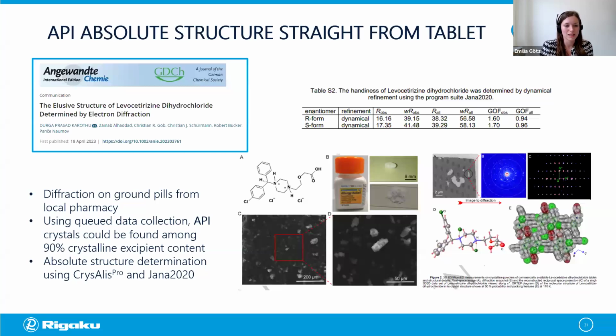And this one here is a really nice example where a pill from a pharmacy was basically ground up and then dispersed on a grid. And then by using queuing, loads of crystals were tested in an unattended way so that the API could be found among all the other things contained in the pill, most of which were also crystalline, so you wouldn't have been able to differentiate them at first glance. And with these data sets, the absolute structure of the API could be solved with a combination of CrysAlisPro and Jana2020, which you've already seen a couple of slides ago.